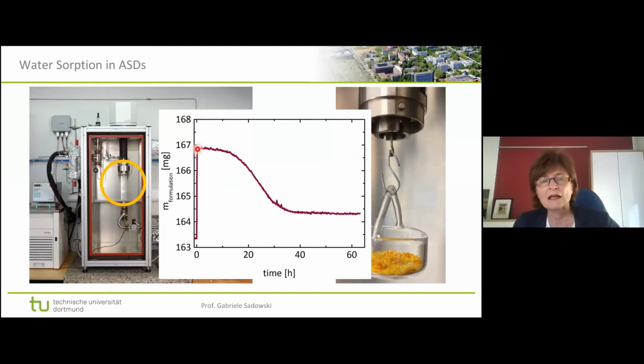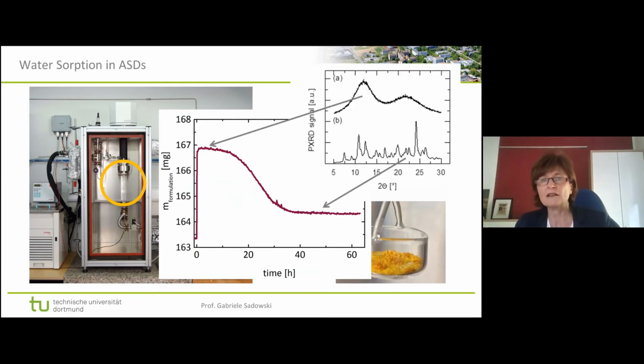And then you see that it stays more or less constant for a while, and then it's decreasing. It's sharply decreasing and then reaching again a plateau. And the question is, what happens here? The decrease is much slower than the increase. We assume that it would be due to crystallization of the API, and that's why we made PXRD measurements. And indeed, what we found is that the sample up here is still amorphous, whereas the sample at the end is